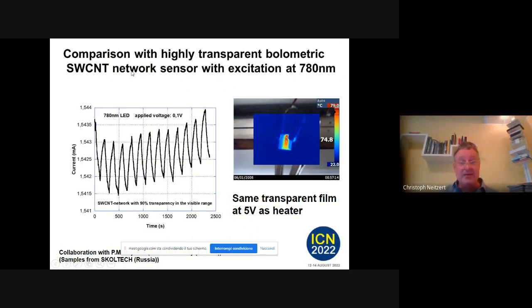This is a very nice network, I have to say. I got it from a PhD student. He has now finished. He went back to India as far as I know. And he got this from Skoltech in Russia. We actually wanted to use them for another reason. This is an almost perfect transparent conductive oxide replacement for solar cells. He made a solar cell just without evaporation, just taking this device and putting it on. He made a kind of record efficiency for this kind of solar cell with these simple, very nice networks.